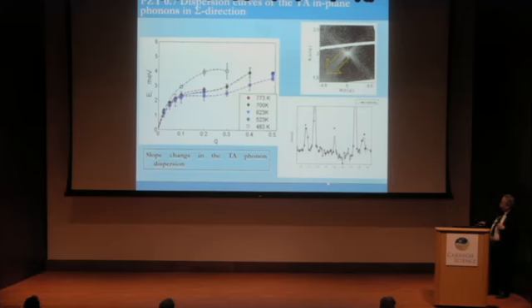You see, not like in pure lead zirconate where we had just a flat dispersion curve, we have clearly, well, at least, if not a minimum, then at least a change of the slope at a finite Q. And this change of the slope is probably the reason that it's not just like in pure lead zirconate, where due to the Umklapp term we create the first order phase transition with (1/4, 1/4, 0). But we have, as I told, an additional incommensurate peak.